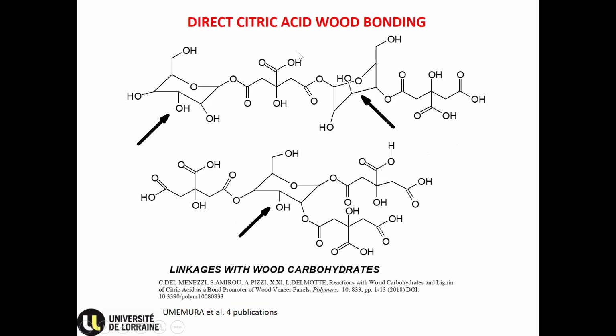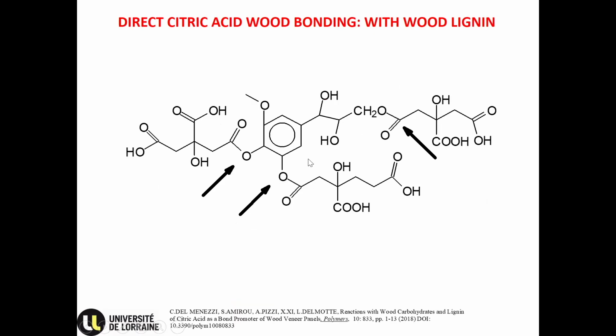Then you've got citric acid. Citric acid is very famous at the moment. It was proposed for the first time by Professor Kenji Umemura, whom I know as a good friend as well, and it was us who explained for the first time what the reaction was. It reacts with the carbohydrates. You can use citric acid with the carbohydrates, so it cross-links the carbohydrates, and it cross-links the lignin as well. It means that you can put citric acid on veneers, and it will cross-link one veneer to the other veneer. It's no problem at all.